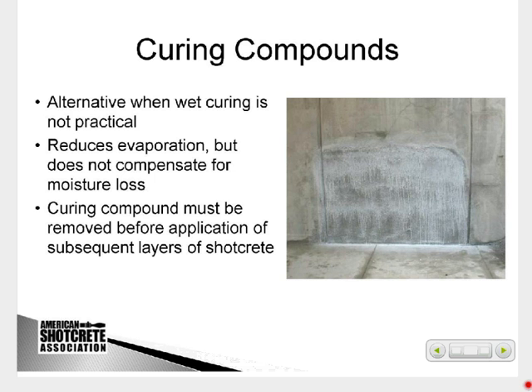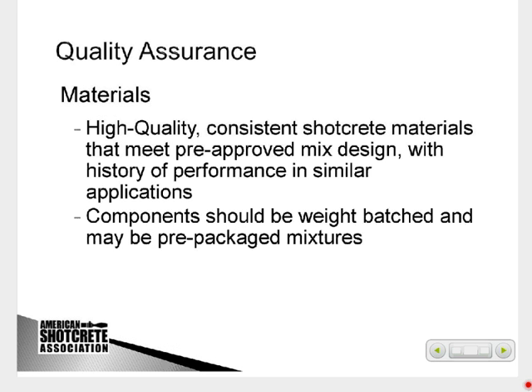If you can't do water curing, we do recommend the membrane cure, the spray-on cure. Because the surface tends to be a little rougher, typically application rates are about twice the manufacturer's quantity of volume that's used per square foot.